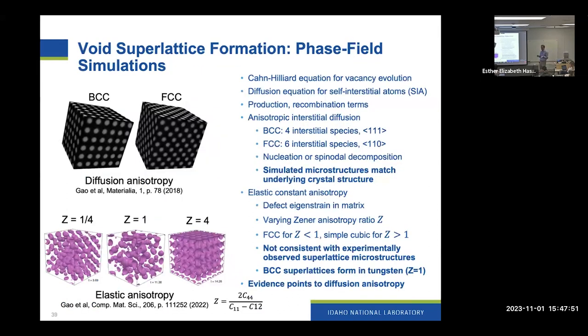So one of the first things we did on this project was figure out what we thought the most likely mechanisms were for this formation. And so we've really focused on elastic anisotropy and diffusion anisotropy. We studied this first with a Cahn-Hilliard type model, where we are only looking at vacancies and void superlattice formation. We then couple that with diffusion type equations for self-interstitial atoms. And the model also has production and recombination terms.